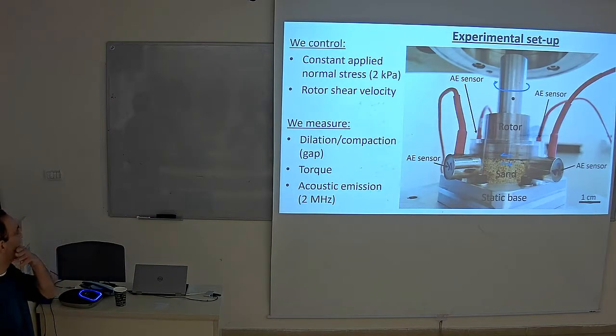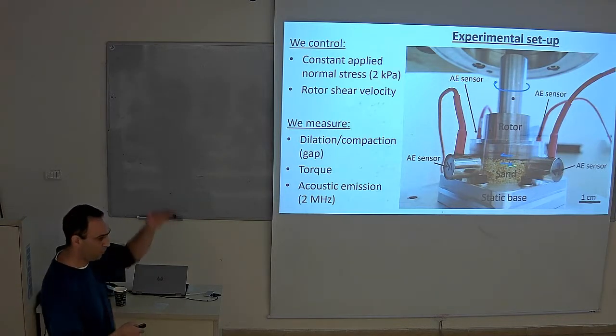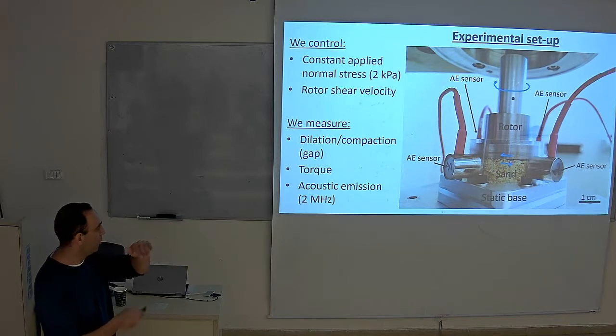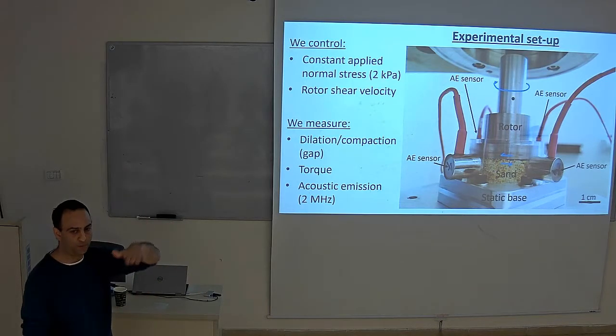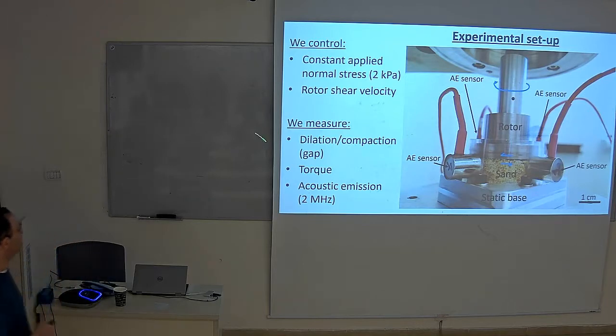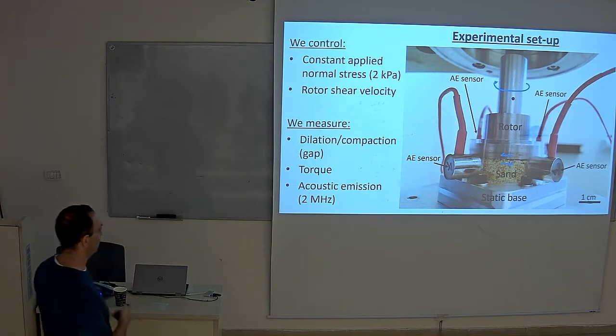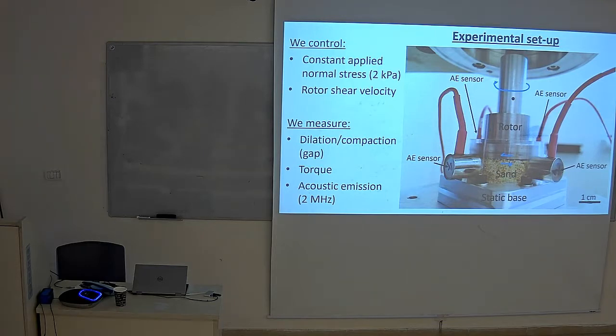So, this is again the experimental setup. You see the acoustic sensors, the sand. Shearing is mostly localized here on the boundary. And what we control in this experiment is usually the constant applied normal stress. So the boundary condition is constant load, which means that the rotor can move up and down in order to preserve this boundary condition. The other thing we control is the rotor shear velocity. So we are telling it what velocity it needs to move at, and I will show you the procedure we have in the next slide.